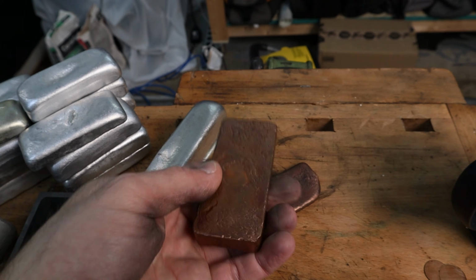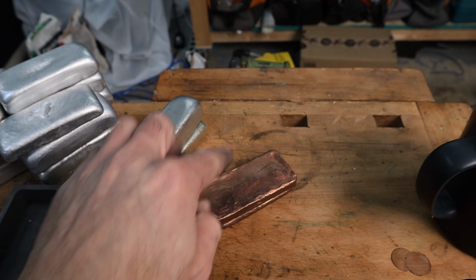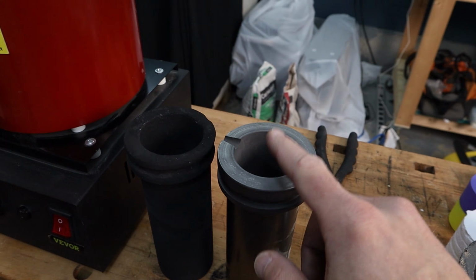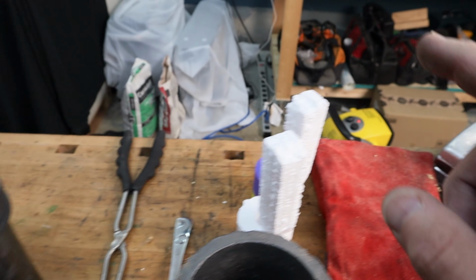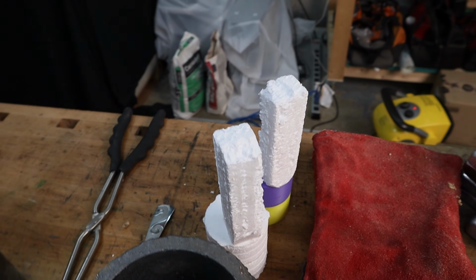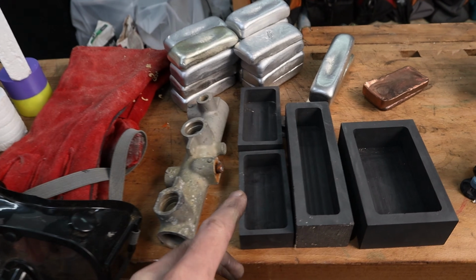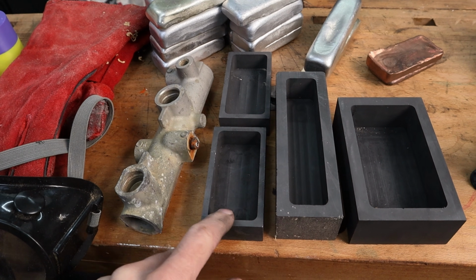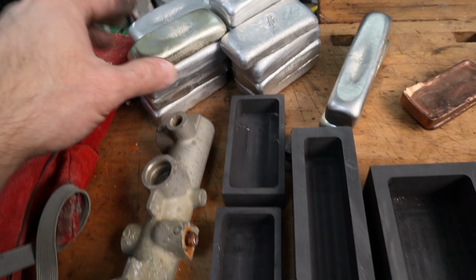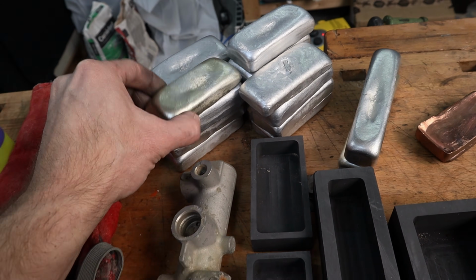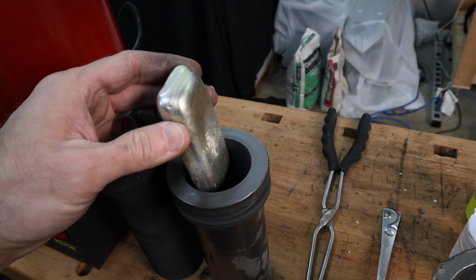I also have some copper that I've done, although copper takes a much higher melting temperature. And when we're casting, we want to make sure we melt more than we need because we do not want to run out a little bit early. We want to make sure we have enough to fill the mold completely. Any excess can be poured into one of these or whatever you have. And then you'll get these little bars that you can put right back in and remelt again.